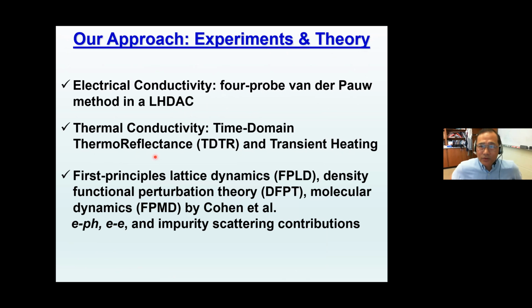So our approaches here are based on experiments and theories. We do electrical conductivity measurements using the four-probe van der Pauw method in a laser-heated diamond anvil cell, together with in situ X-ray diffraction. We measure the thermal conductivity through time domain thermoreflectance.